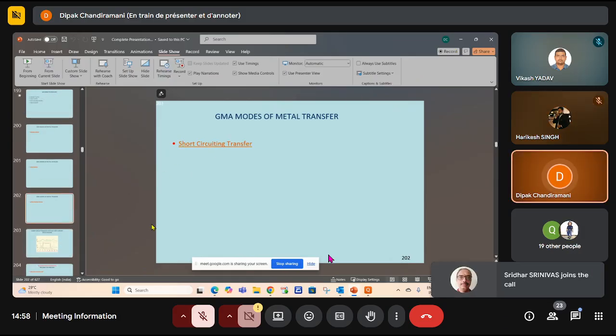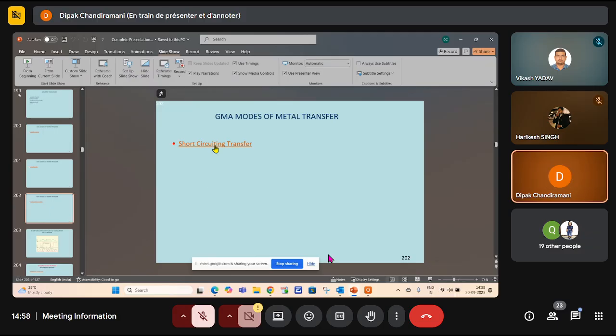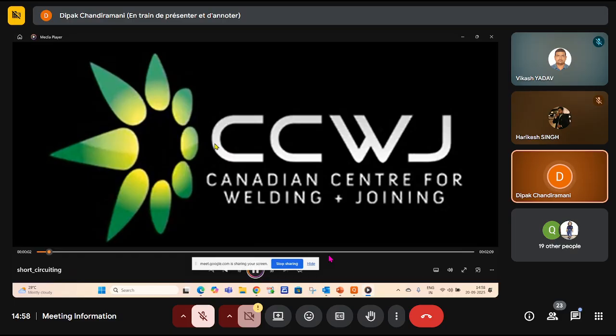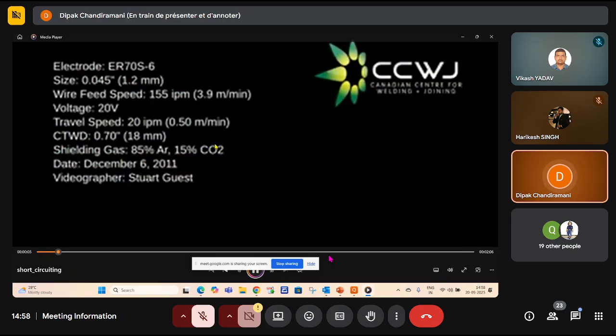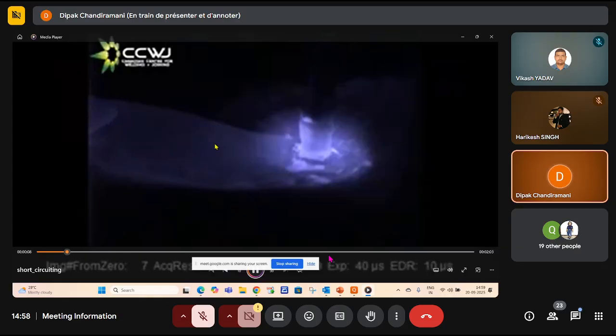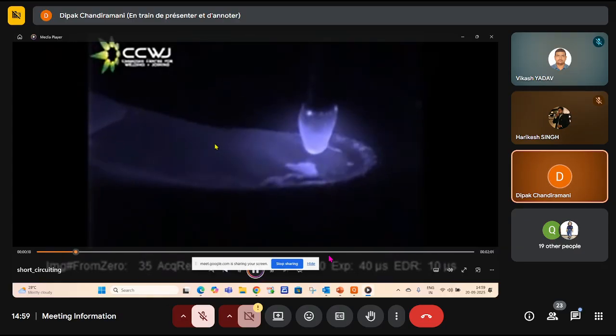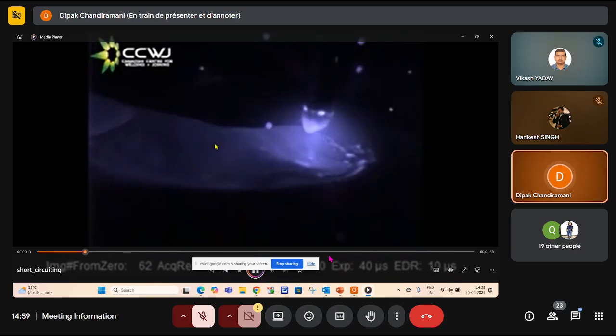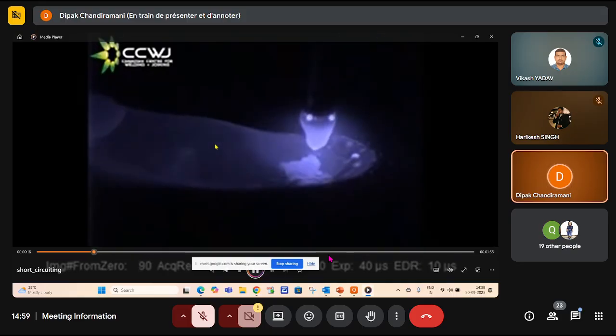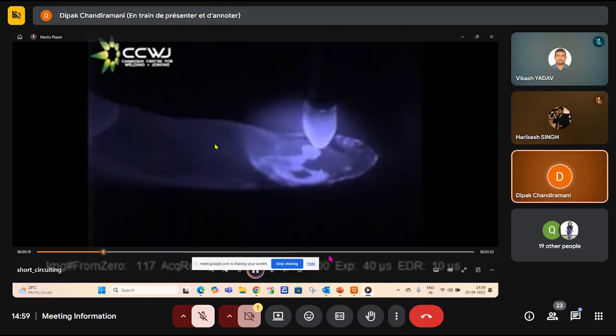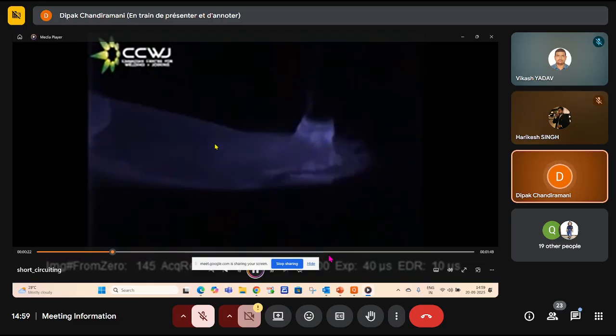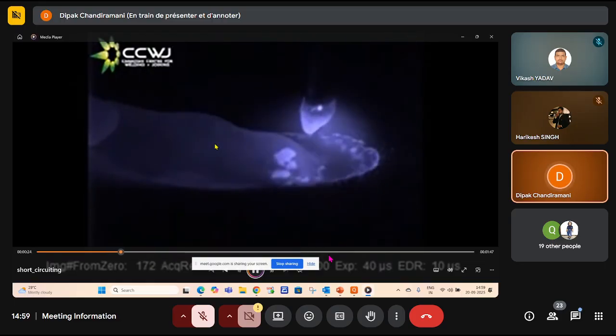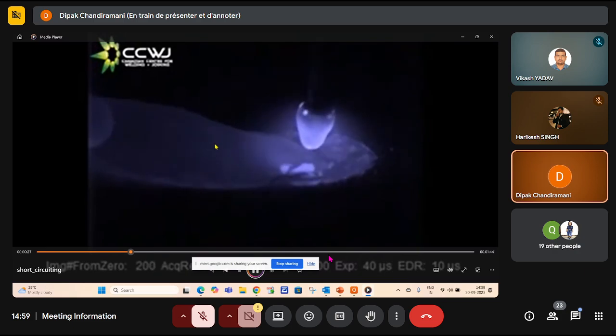Then we have what is called short circuiting transfer. This is the thing where you have to be careful about your qualification. See the difference between the previous two and this. You can see apart from the welding condition, voltage is very low. That time it was 35, now it's only 20. So you get a very short arc length. And you can see as the droplet is forming, it is so close that it goes and touches the weld pool and there's a short circuit. Then, like a fuse blows, the short circuit is clearing itself with some spatter and you get another droplet.